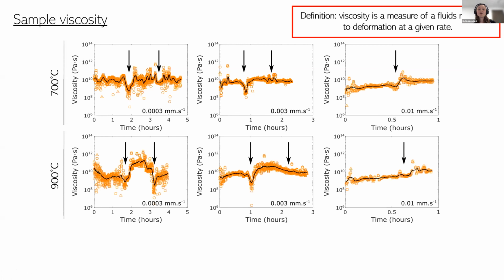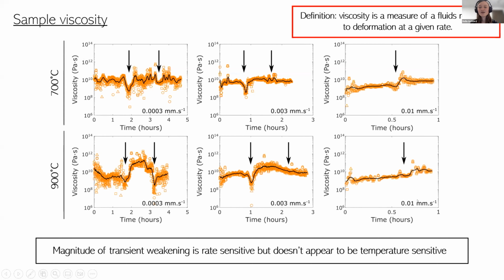We can do the same set of experiments at a higher temperature to see if temperature has any effect on this. And again, when we're pushing very slowly, you see these drops in viscosity when you go through that transition, but they become less prevalent when you go to higher strain rates. So we have transient weakening in this quartz to coesite transition, but now we want to use microscopy to see if we can understand it a little bit more.